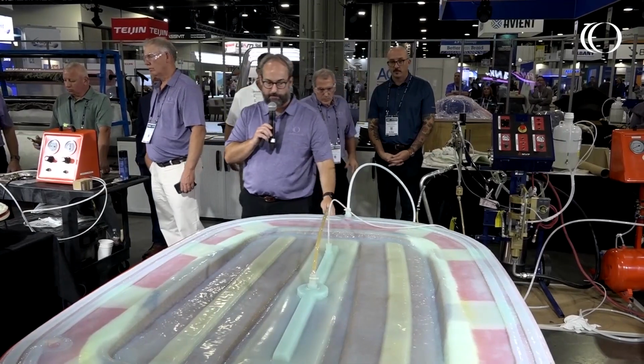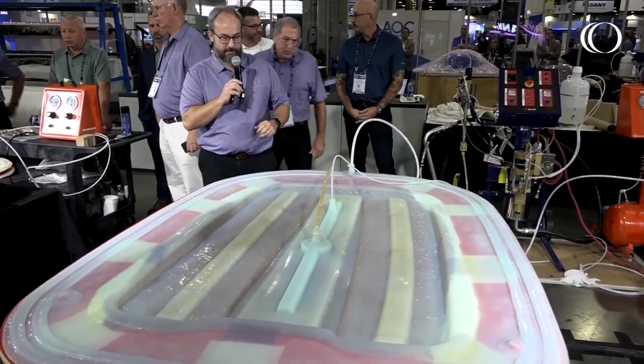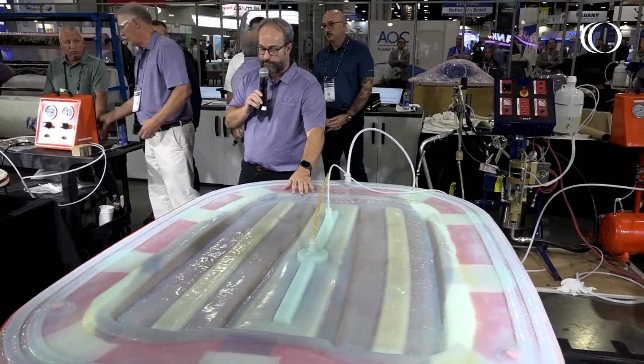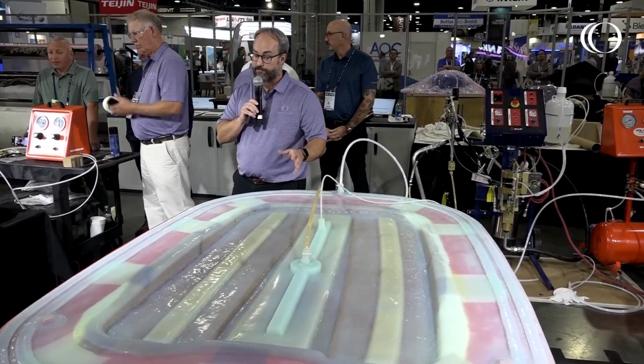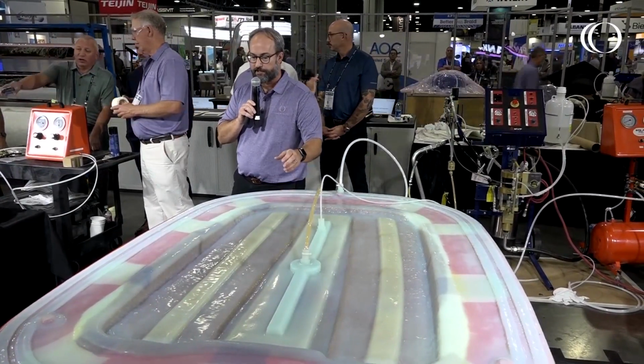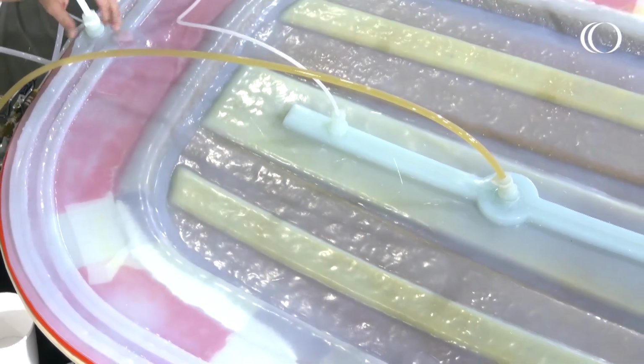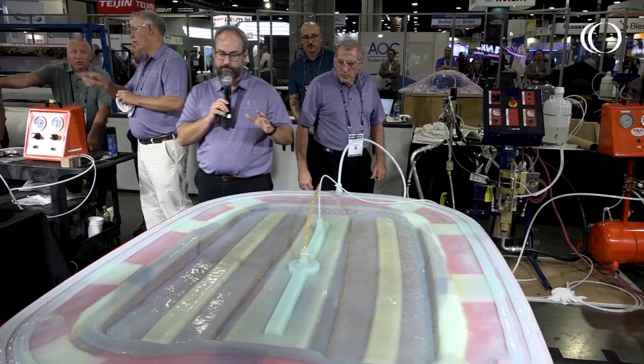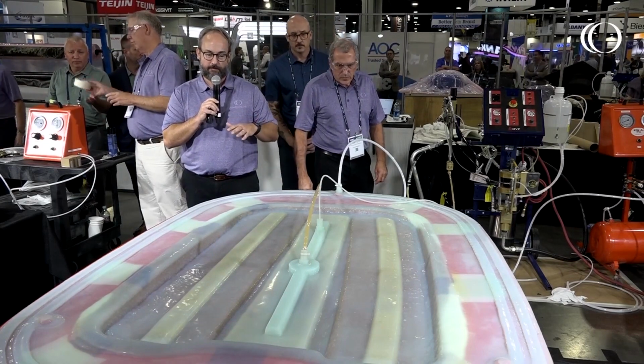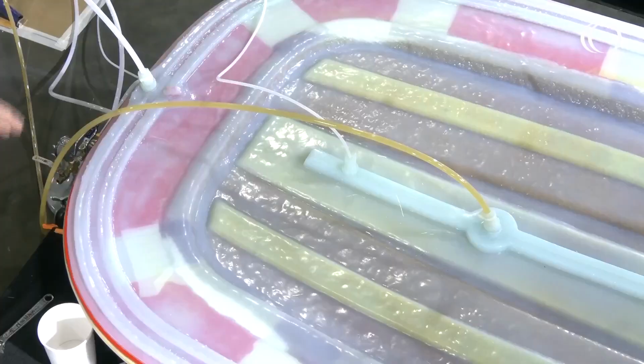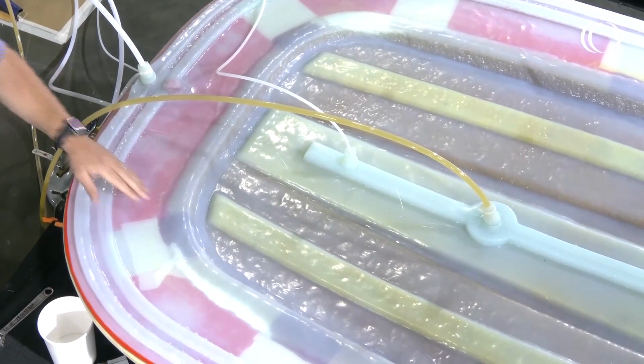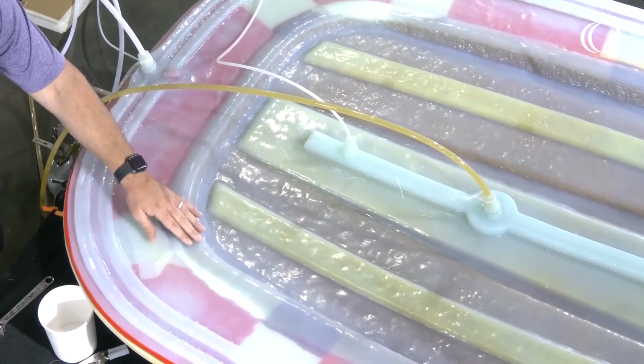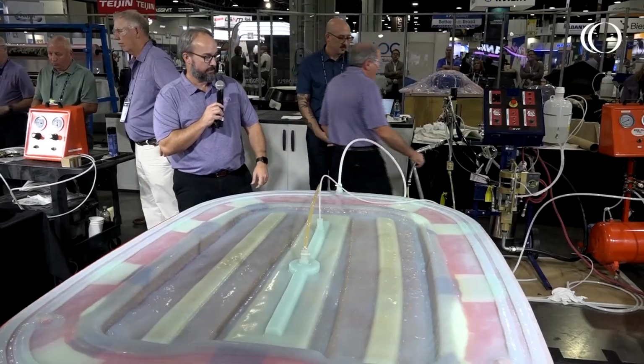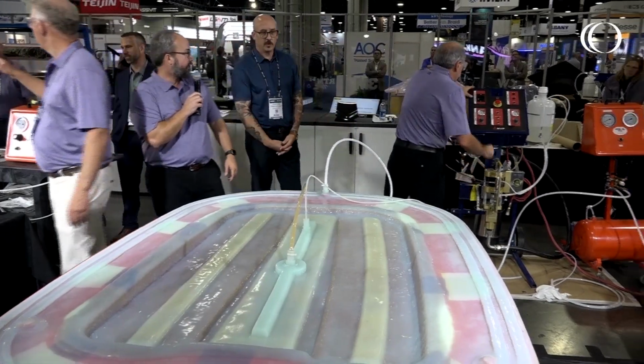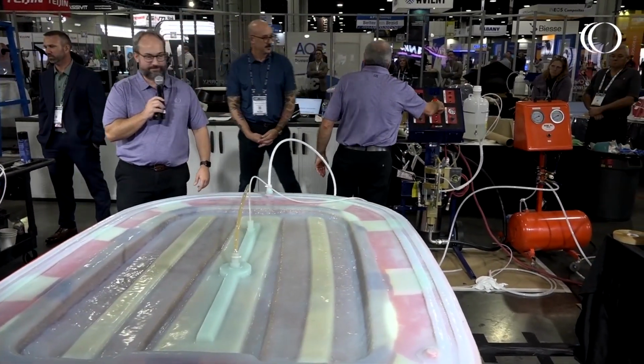So we've stopped this one temporarily just to let it fill a little bit. One of the things with the silicone bag is you can actually pump it in faster than the laminate will take the resin, and it'll lift the bag up and balloon the bag. You have to be very careful doing that because you could outrace the laminate and not have a wet surface on the mold side. So Dan has slowed the machine down to, we probably have enough resin in there already to finish the part. So I think he's done. He's about ready to stop and put a couple more strokes.